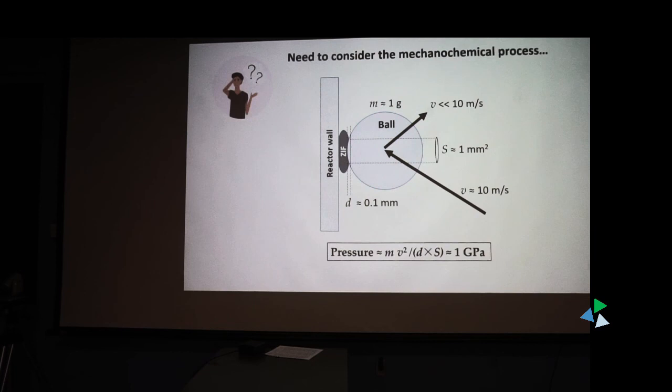So here is what happens in the mechanochemical process. You have some pieces of material stuck on the reactor walls. For example, you have a piece of ZIF stuck on the wall, and you have a ball striking on it very hard. So something happens. This is the source of the transformation of the ZIFs, and intuitively we can understand that the strongest ZIFs will survive such impacts, while the weakest ones will be destroyed. So from this simple order of magnitude, we consider that